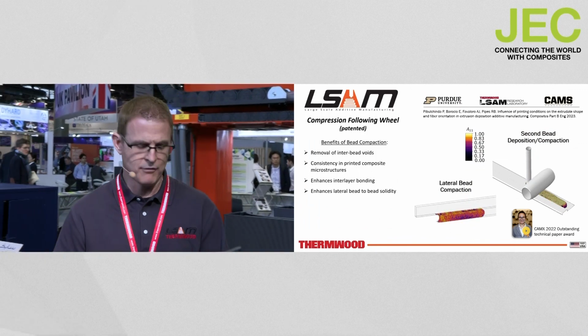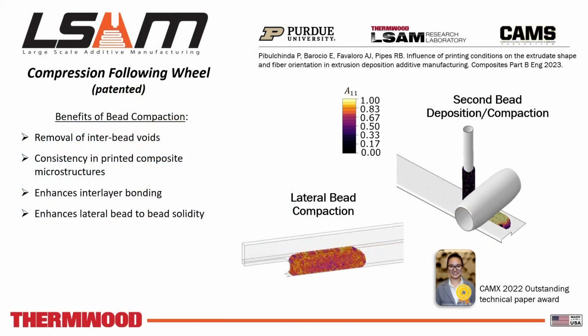A study performed by a group at the LSAM Research Laboratory further emphasizes the benefits of this active bead compaction. Bead compaction aids in the removal of inter-bead voids. It improves the consistency in the printed composite microstructure, which also includes repeatable fiber orientation. It enhances interlayer bonding and provides the best results for lateral bead-to-bead solidity.